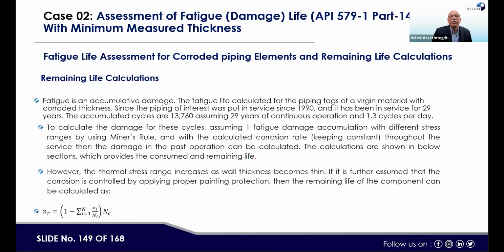Like a fatigue life assessment for corroded piping element remaining life calculation. If I read it, because it's a result, the fatigue life is an accumulative damage. The fatigue life calculated for piping tags for a virgin material with corroded thickness, since the piping of interest was put in service in 1990 and it has been in service for 29 years. The accumulated cycle is 13,760, assuming 29 years of continuous operational life and 1.3 cycles per day.